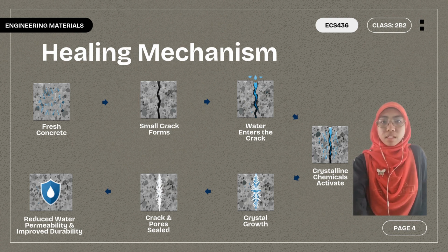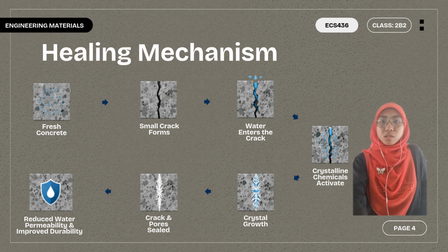Once activated, these chemicals react with moisture and unhydrated cement particles. This chemical reaction produces insoluble crystals that begin to grow inside the cracks, pores, and tiny capillary channels. As the crystals continue to grow, they completely fill the empty spaces and block the pathways through which water can travel. This reduces water permeability and protects the steel reinforcement inside the concrete from corrosion.